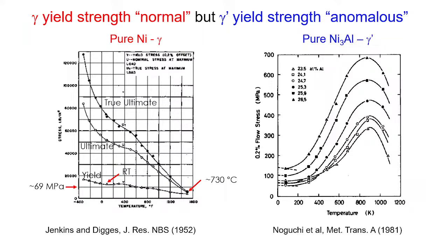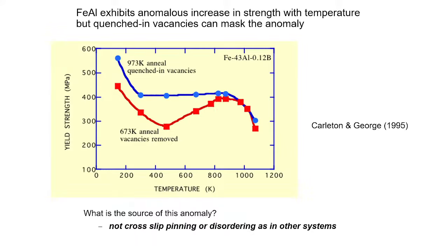So several years ago, we started looking to see whether there were other systems, not the high temperature nickel system, but iron-based systems used at lower temperatures, that might show the same effect. And surprisingly, there are some systems that do, though the mechanism is different. In the nickel to aluminum case, the temperature dependence is because of dislocations cross-slipping and getting caught up during the cross-slip process. Here it's due to vacancies. And initially, people never saw this unusual temperature dependence. This is what it looked like: the sort of traditional BCC-like behavior, with a strong temperature dependence here, a relatively flat region over here, and then a drop-off at high temperatures.